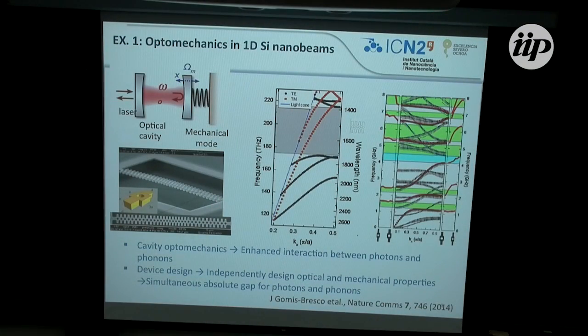I want to give you two examples of the work we do in the group, and you'll see the connection to phonons and films and silicon. The first one refers to the interaction of mechanical modes with light. So this is in the range of optomechanics, coupling the motion due to light pressure to a mechanical mode, here depicted as a spring. In reality, these systems use a nanobeam. It's a silicon suspended nanobeam, which is designed in such a way that it has a phononic and a photonic band structure. So here you see the light cone, and this is my phononic part with a phononic gap. And here you see the dispersion relation as the band for the mechanical modes also with a gap.